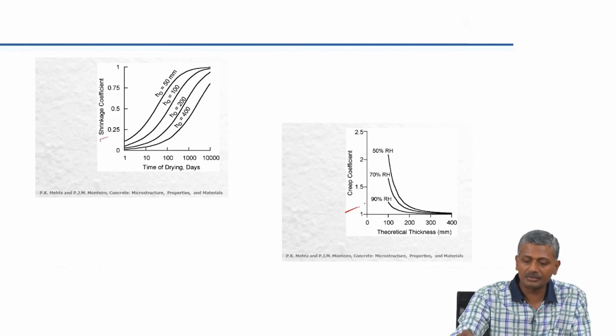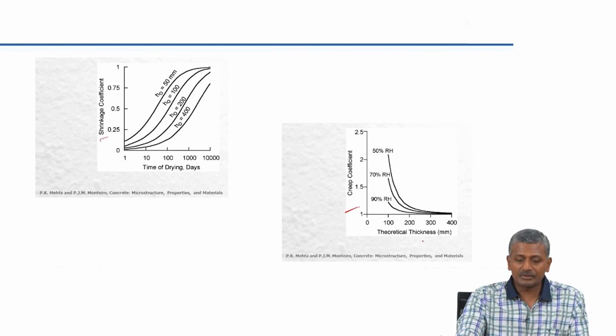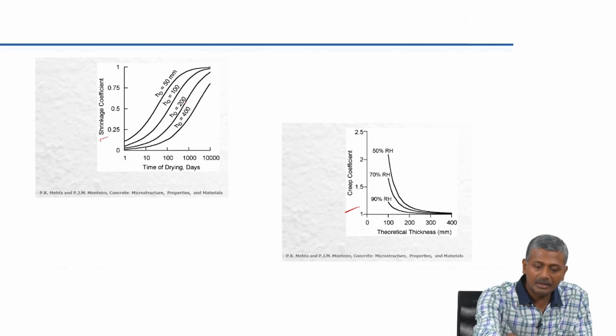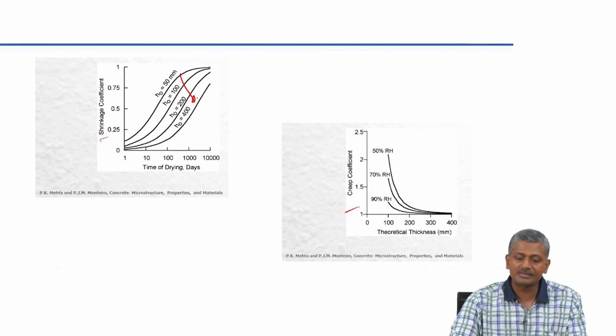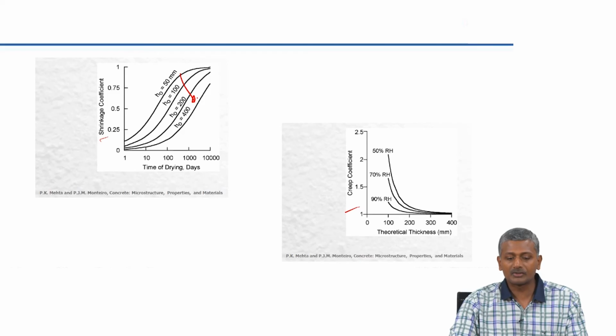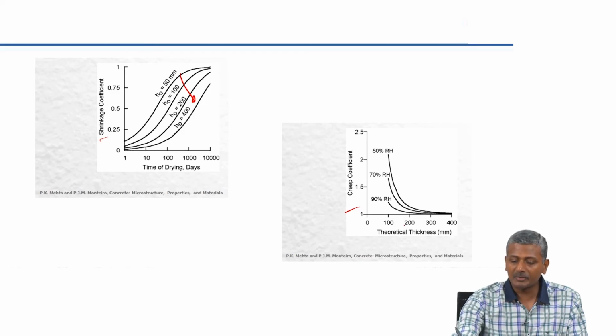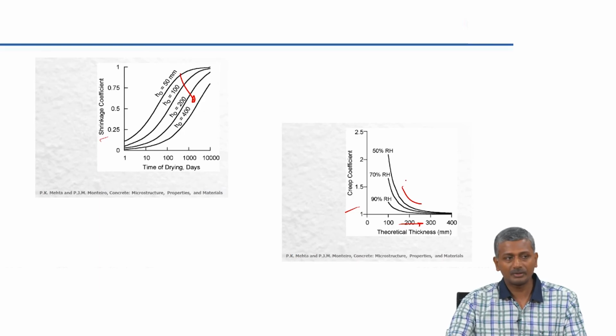Again, this is showing you similar results here in terms of shrinkage and creep coefficients with respect to the thickness of the material. So, again as the thickness of the member increases, you are getting lower and lower rates of shrinkage. As the thickness of the material increases, you are getting lower and lower rates of creep at different relative humidities. Okay.